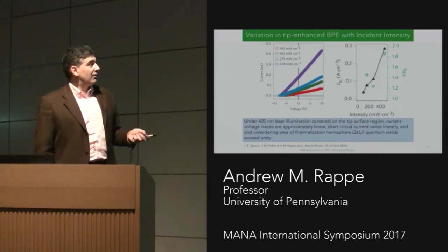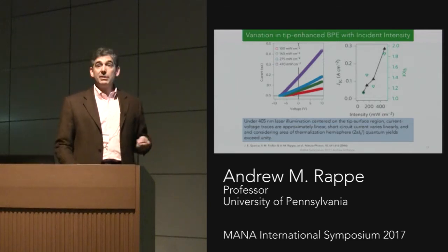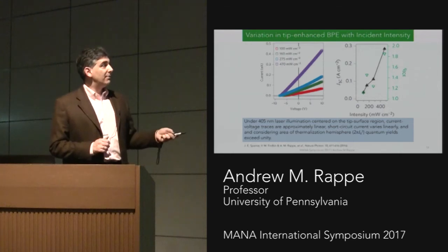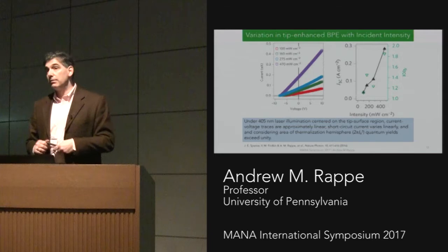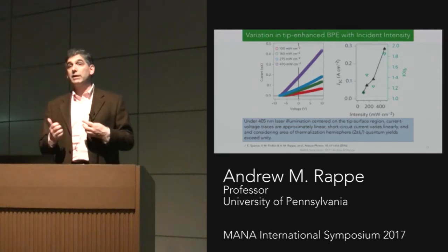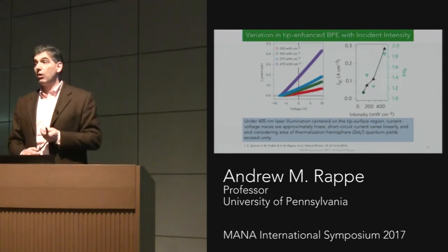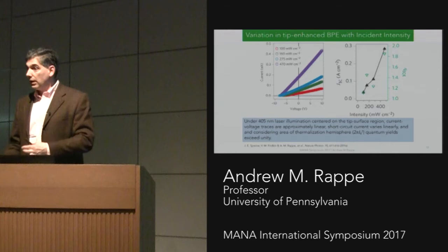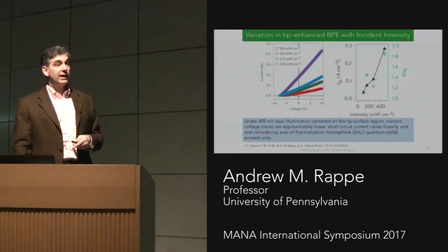Okay, so one thing that I would draw your attention to is that the external quantum efficiency, this means the number of electrons per photon, can be greater than 1. And so this experiment, this is the bulk photovoltaic effect with the nanoscale tip, is observing impact ionization or other effects such that one photo-generated carrier leads to more than one electrically detected carrier.